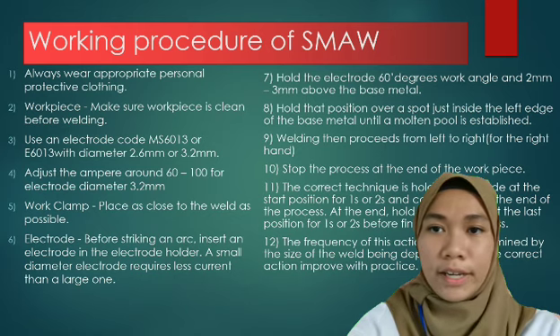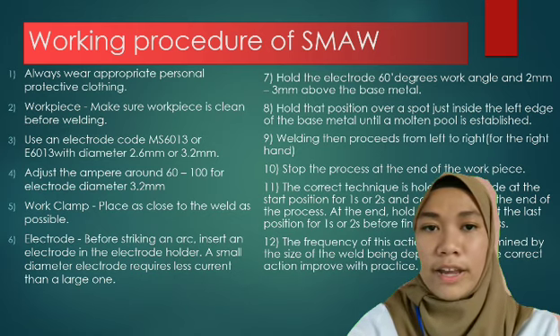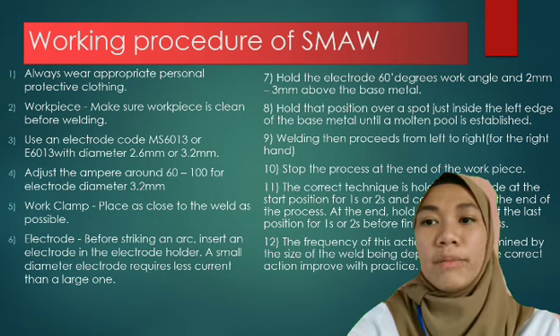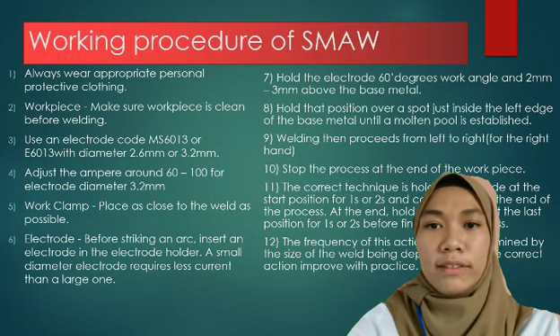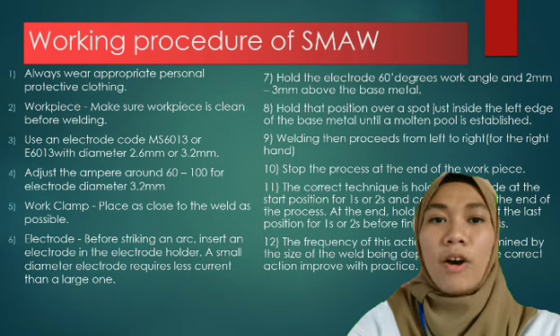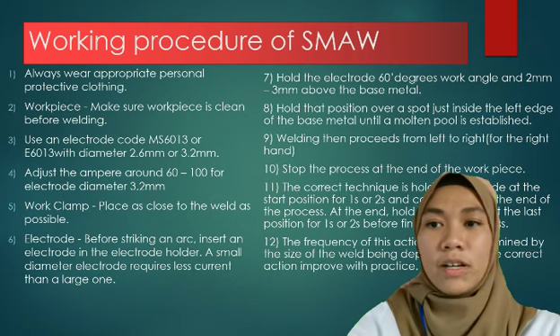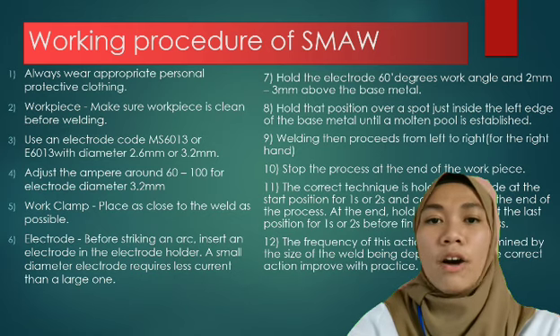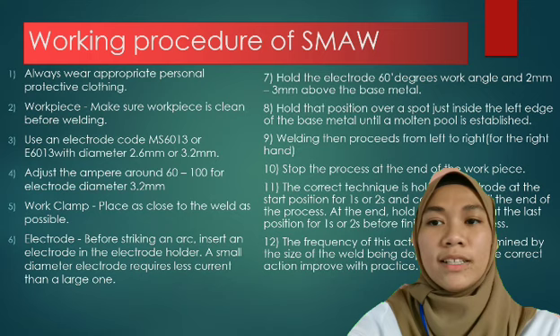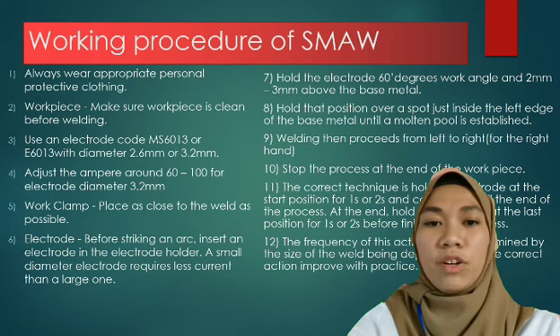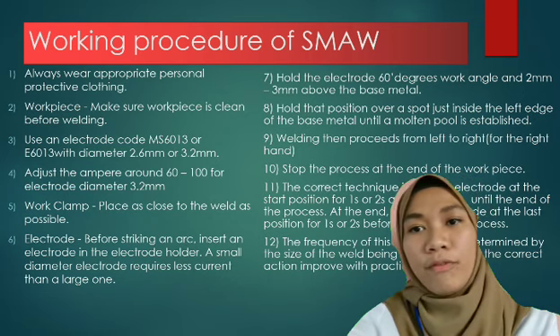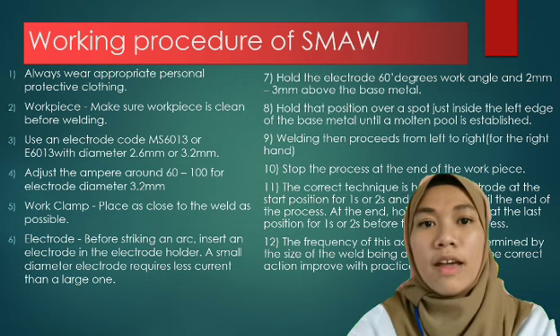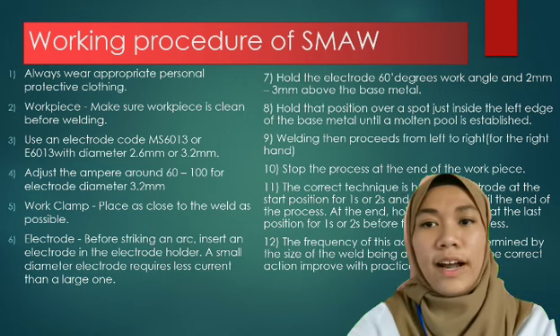Before striking an arc, insert an electrode in the electrode holder. A small diameter electrode requires less current than a large one. Next, hold the electrode at a 60 degrees work angle and 2 until 3 mm above the base metal. Hold that position over a spot just inside the left edge of the metal until a molten pool is established. Then welding proceeds from left to right for the right hand. Stop the process at the end of the workpiece.